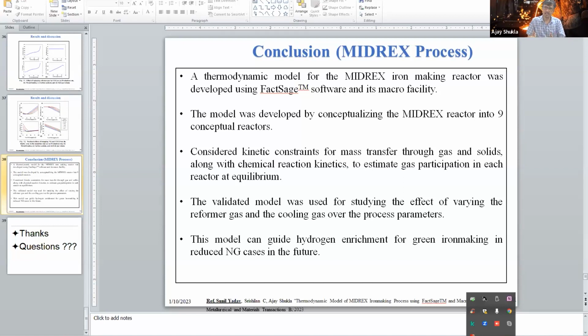So my idea is that I'm not saying the process in totality is in equilibrium. I'm saying that some localized regions are in equilibrium, and those regions are defined with multiple reactors in the system, which are interconnected with the bulk regions which are not in equilibrium. The process is divided into a number of time steps, and in this way the phenomena are governed. We make certain calculations, and then by validating against the real process in a cyclic manner, we recalculate those coefficients, and finally we arrive at the coefficients which are the true representation of the actual process. This is my strategy.